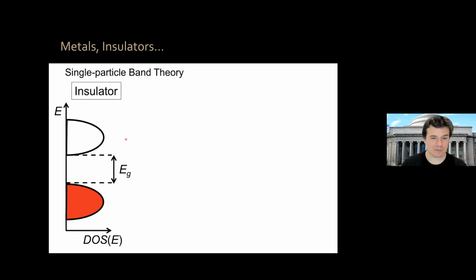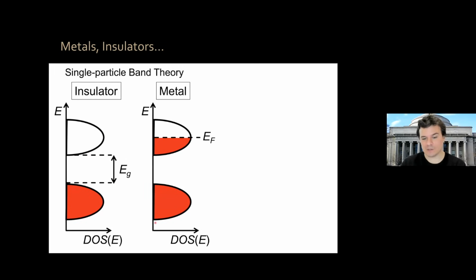If, on the other hand, we have a material which, similarly to before, we have the density of states, these are the bands, okay? And now one of the bands is completely occupied with electrons, but the other one, let's say, is half occupied with electrons, so that your Fermi energy is here. Now you can see that we have, at infinitesimally low energies, free available energy states for electrons to be excited via a bias voltage or via temperature so that the material can conduct. And this is a metal, okay?